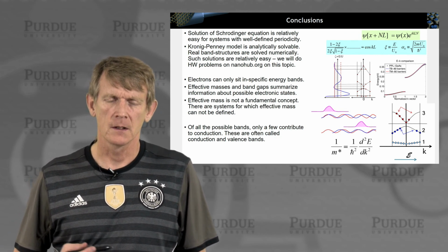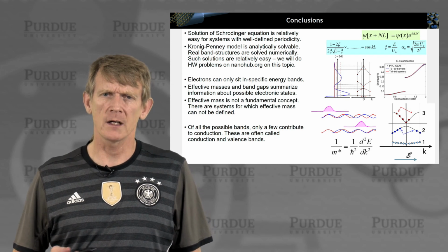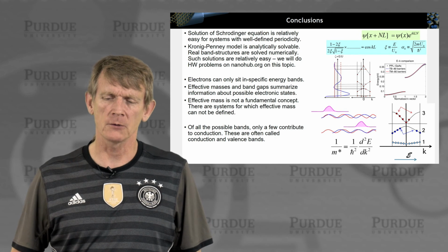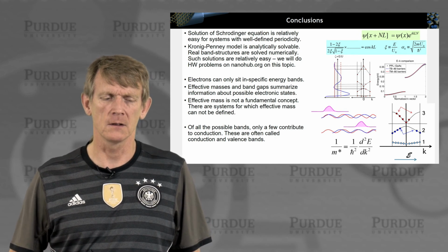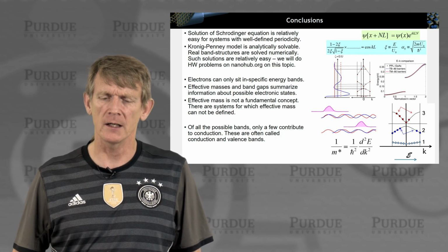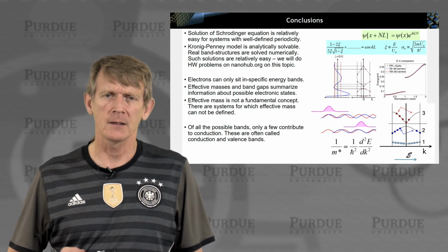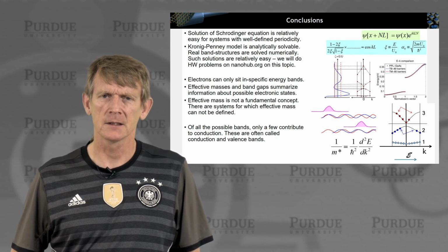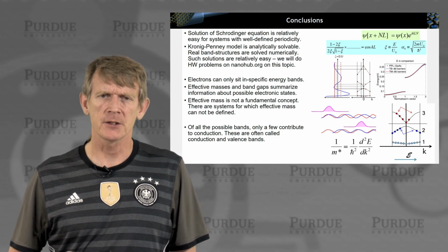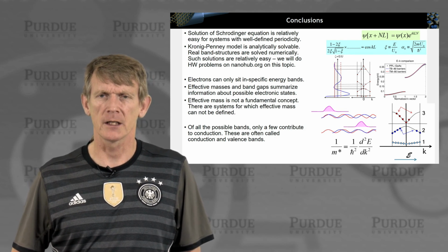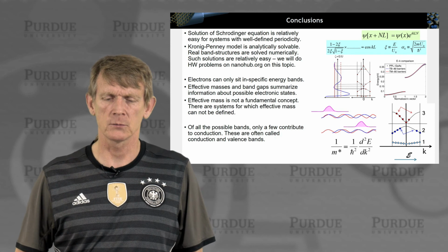So calculation of the Schrödinger equation in a square potential well with periodic boundary conditions is reasonably easily done. It's called the Kronig-Penney model, and you can derive fundamental band properties in solids from it. We have compared that to transmission coefficient-based methods and seen that we get extremely similar results.